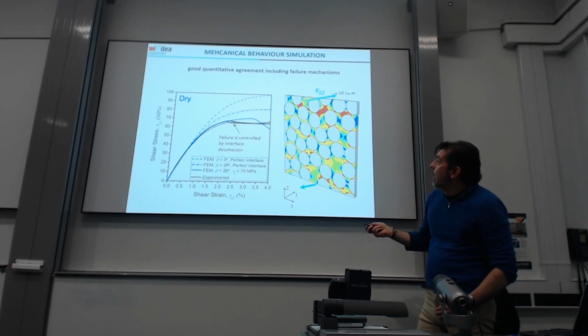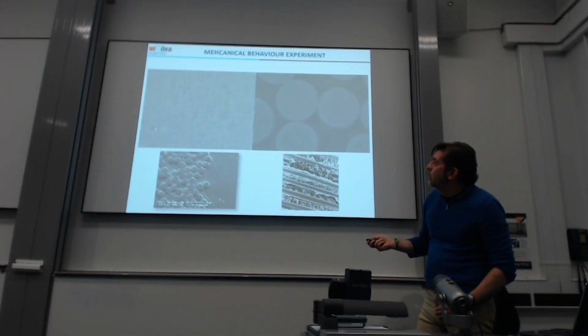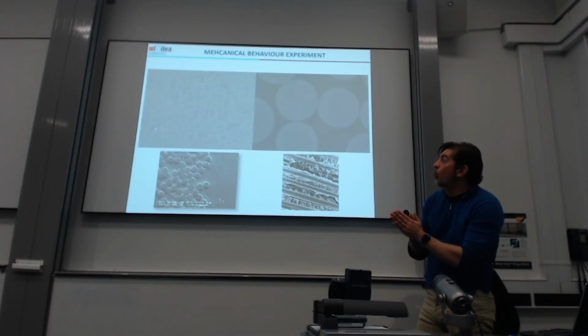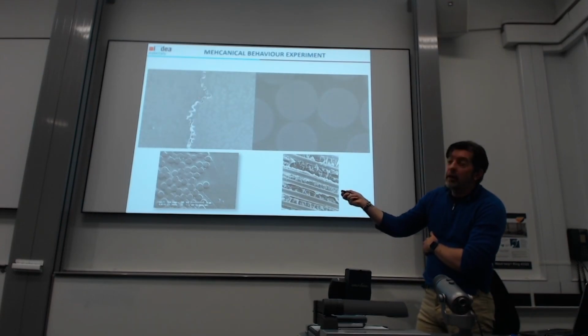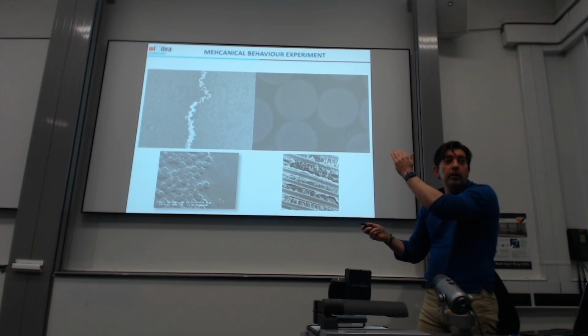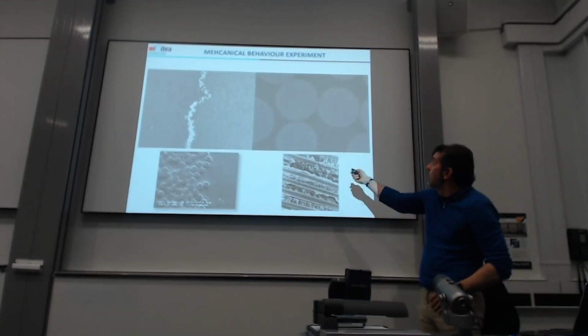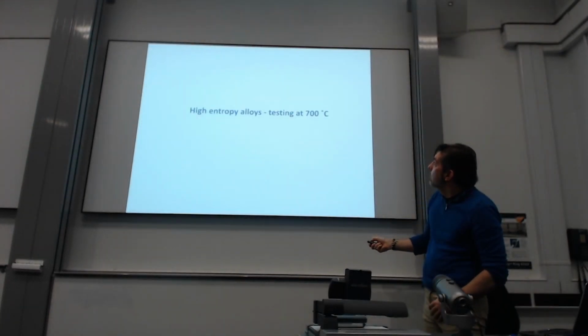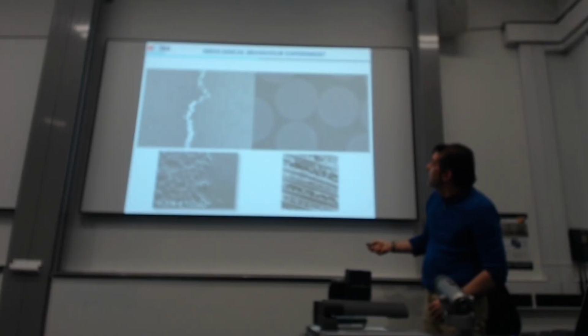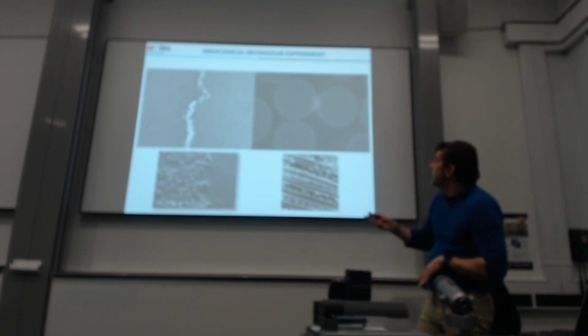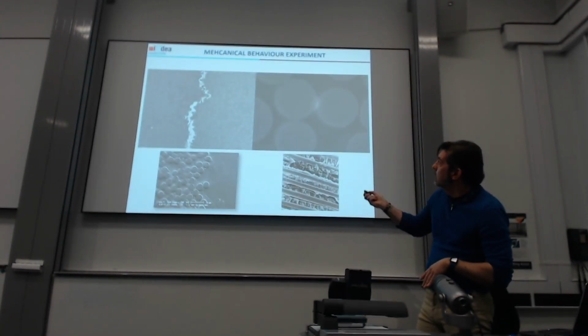We can see in this image, this is a mode 1 of deformation, and you will see the material is failing through the interfaces. Like the same here. You can see some debonding there. Maybe at high temperature, what will yield first is the matrix, but you need to measure the strength of your interface. It's opening in here.